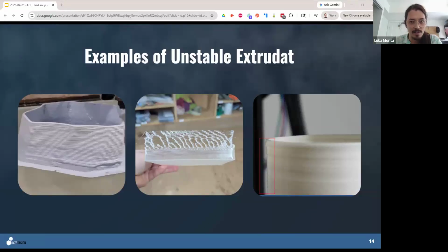And this loops back to what Dan was talking about too, actually. But we did find that while reducing the layer height would compress these interlayer voids a little bit better, we would find these compressibility and back pressure issues that brought us back to the issue that he was talking about, where it would actively change the flow rates that we received over time with this kind of transient response. And it was really interesting. But yeah, also definitely keeping an eye out on print porosity and even how that interacts with retraction points as well. It's all very interesting stuff.